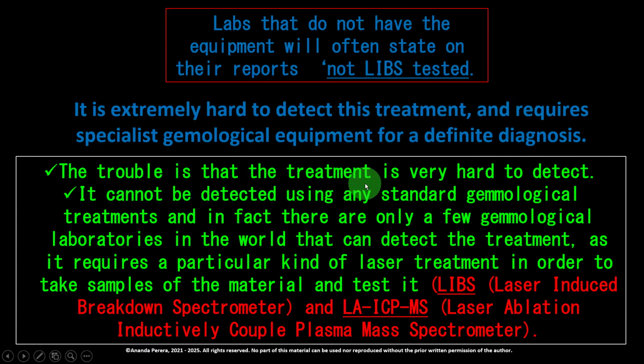The trouble is that the treatment is very hard to detect. It cannot be detected using any standard gemological tests. In fact, there are only a few gemological laboratories in the world that can detect the treatment, as it requires a particular kind of laser in order to take samples of the material and test it. It is LIBS, meaning L for laser, I for induced, B for breakdown, S for spectrometer. The shortened form is LIBS.